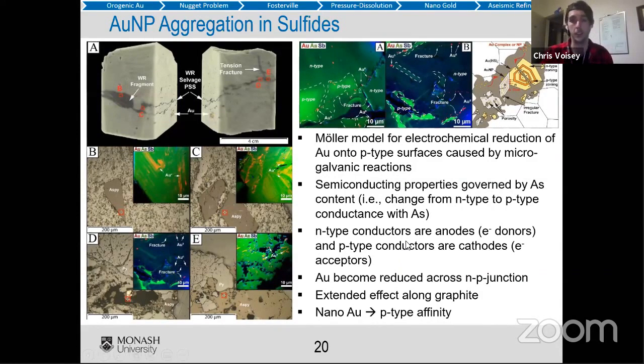The type of conductance of arsenopyrite or pyrite changes based on its arsenic content. So if you increase the arsenic content in a pyrite, the zones that have a lot of arsenic in them will actually become P conductors, and the ones without a lot of arsenic will be N-type conductors. And the way the Möller model works is that if you have an N-type and a P-type conductor together, so one that takes electrons and one that donates them, you can actually shoot electrons across these surfaces. If you had a gold-bearing solution, which was connected to hydrogen sulfide or whatever, you can reduce it by hitting it with an electron, and you do it by having these two different kinds of conductors next to one another.